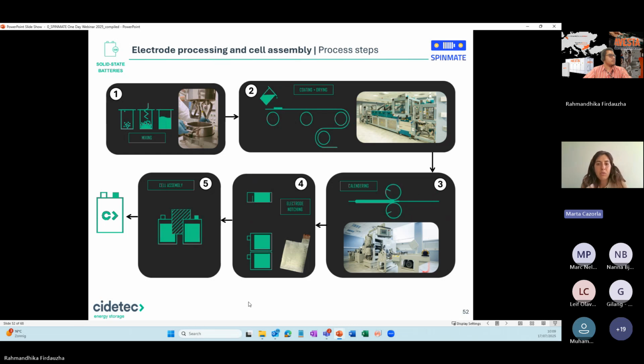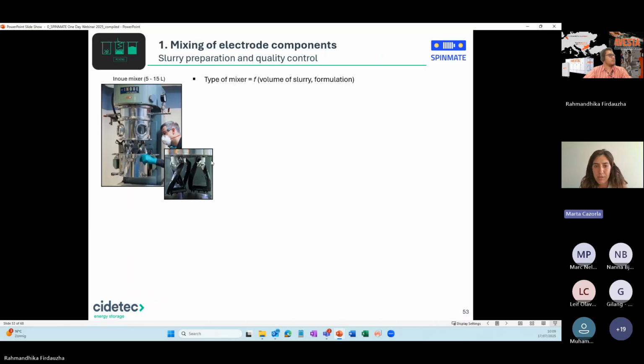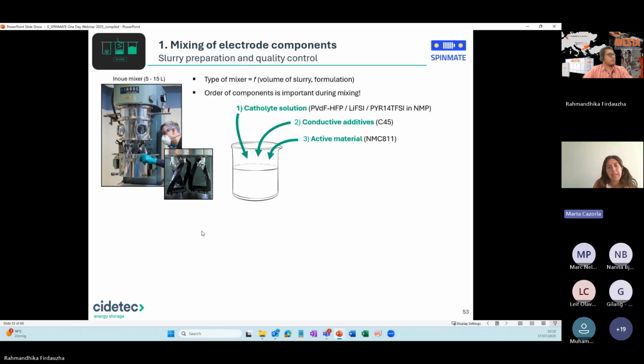So now if we go a bit into each step, mixing the electrode components: if we're preparing such big slurries, then we need powerful and appropriate mixers. So we have different types of mixers depending on the volume of slurry and the formulation we're working with. This is an example of the mixer that was used in SPINMATE. And another parameter that is very important when we're doing the mixing, next point please, is how we mix these components, the order.